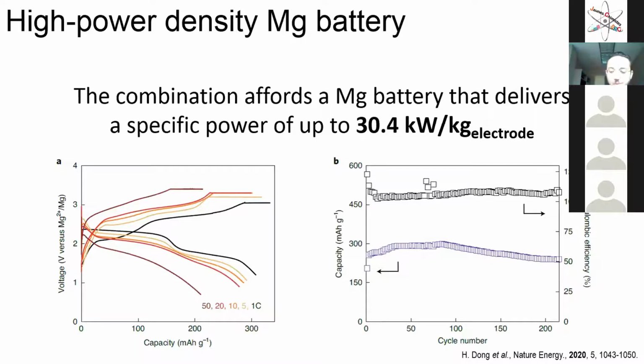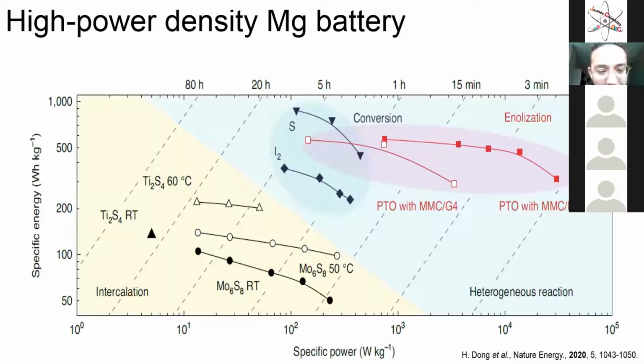So if we compare this with other magnesium batteries, you have on the left magnesium batteries that are based on sulfide. Most of them require high temperature for cycling. Then you have sulfur on the top in blue, that provides more energy density and power density. And then you have the organic magnesium batteries that can provide much more energy density and power density. And here this is what we can do with organic materials.